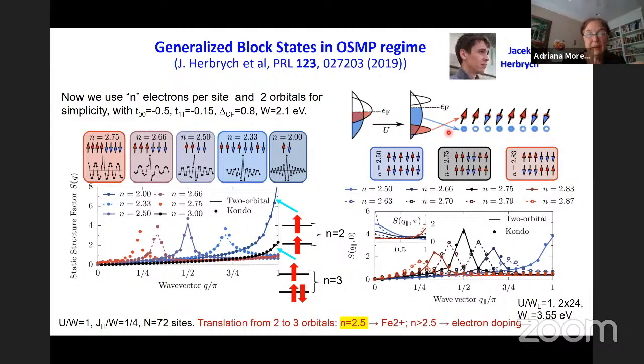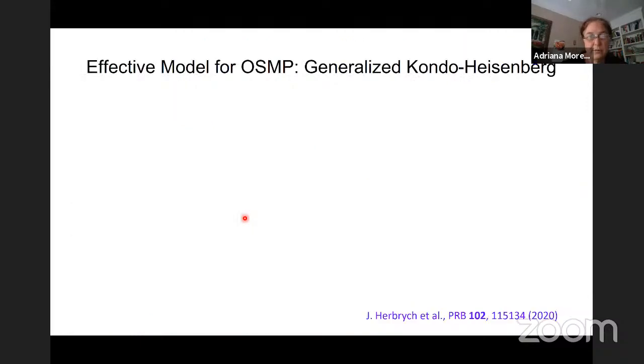So in order to do better, we introduced an additional simplification. You can see here that the lines correspond to the result for the two-orbital model that I just described. And then we have all these points that are in very good agreement with the lines, which I label Kondo. This is an effective Kondo model that we constructed just to study the multi-orbital Hubbard model in the orbital selective Mott phase. So this is the idea.